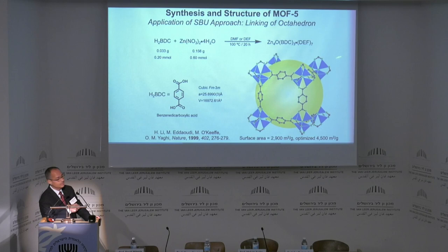And now the organics can be functionalized, and the metal oxide units, of course, the metals can be varied, the clustering can be varied. Later on, a few years later, we optimized the porosity, and it turns out it's much, much higher than we thought it was. What I mean by optimizing porosity is that we learned how to remove the guests from the pores completely and get the true porosity of the material.